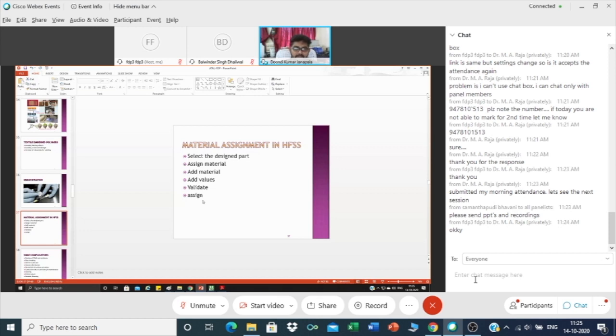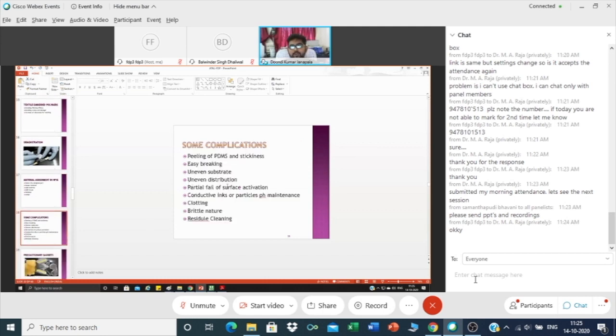In a similar way, as you added the dielectric properties of the polymer, you can add the conductive part also. So that is how you work with it. So assigning material, these are the steps that I showed. Some complication: if you are not curing your polymer properly, then it will be a little bit sticky, and while peeling off it will break. And sometimes some of the polymer will stick to your particular mold. In some cases, beginners can use a universal mold releaser spray, a silicone-based universal spray. Spray your particular mold with that and clean it, and then you pour the PDMS and it will peel easily.